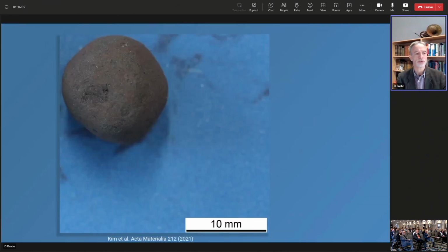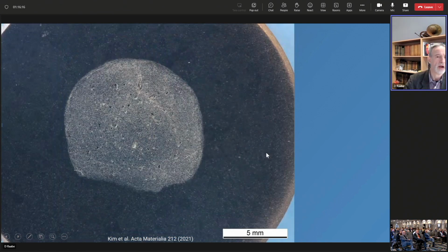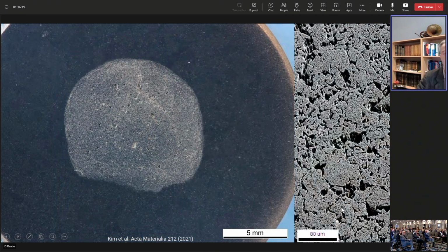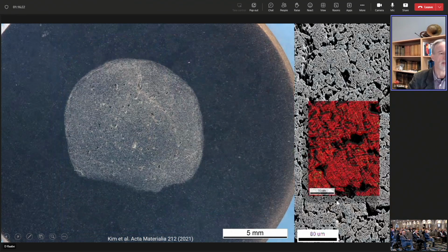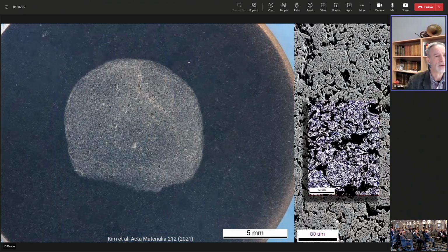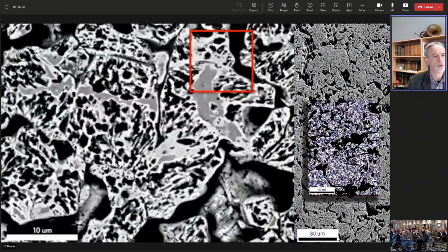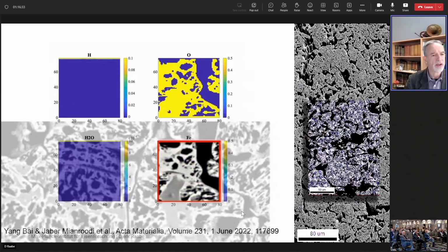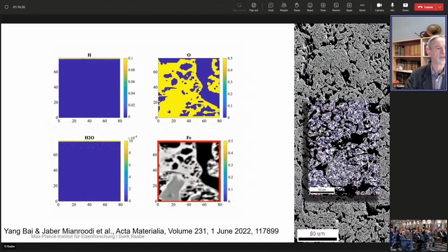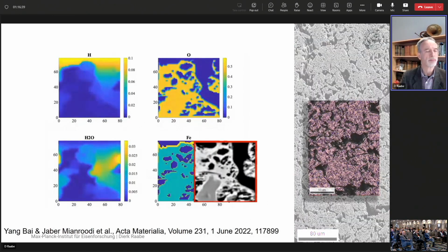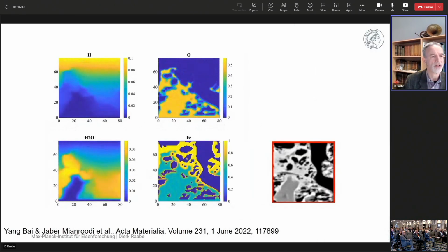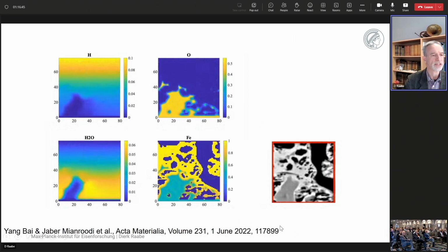Another point is the boundary condition treatment. Here you see a commercial pellet, a little bit bigger than a centimeter in diameter. So I mentioned already, you can cut it open. You see the rich polycrystalline microstructure, the inherited porosity, and so on, similar to what I've shown you before. You can make the phase contrast analysis. But then we cast all of this into a corresponding Ginzburg-Landau calculation, so in a phase field model where we solve on the one hand the Cahn-Hilliard equation for the transport. We have the corresponding chemical reactions implemented to produce the water, and of course an Allen-Cahn theory that tracks the progress of the phase transformation.